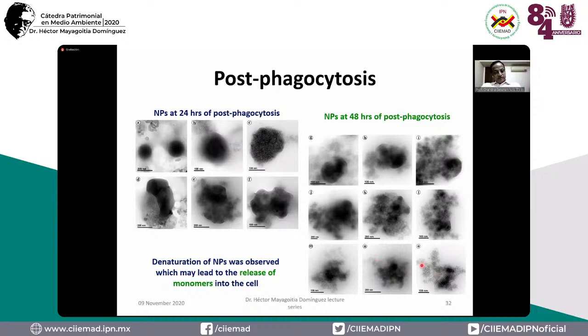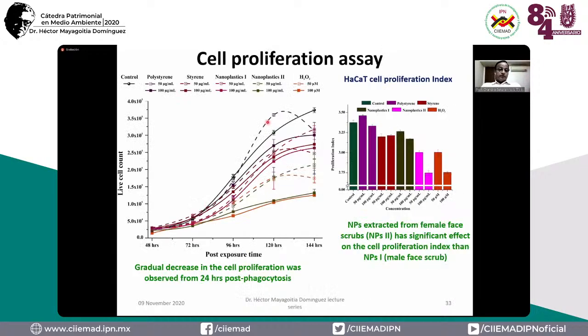And we could see a release of a polymer subunit of nanopolystyrene, the styrene, in our GCMS analysis. That means denaturation of nanopolystyrene was observed, which may lead to the release of monomers into the cell. The monomer here is styrene, and styrene is carcinogenic, which is cancer causing. So these are some of the experiments.